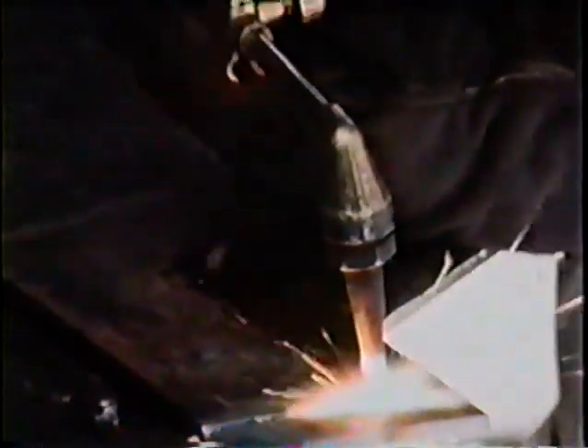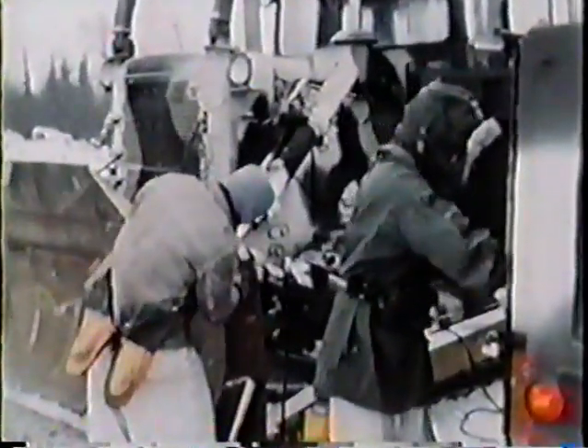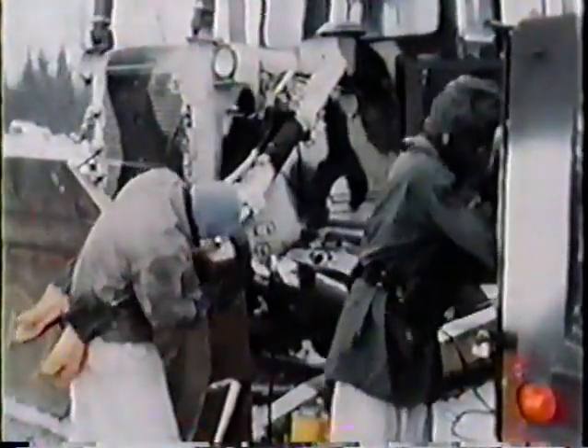For cracks in certain structures, such as frames and supporting arms, you need to add a reinforcement plate, or fish plate as it's called. Follow the guidance in the current publication for this type of repair. It's important to note that you do not continue the welding bead entirely around the plate. Making the reinforcement rigid in this way would merely transfer the stresses that caused the crack or break to the plate,